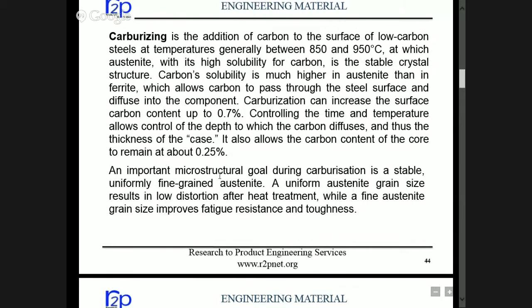So an important microstructure goal during carburizing is a stable, uniformly fine grain austenite. A uniform austenite grain size results in low distortion after heat treatment, while a fine austenite grain improves fatigue resistance and toughness. So the whole process results in a harder case for bearing the load, and a tough core in case of impact loading cases. And the stabilization is achieved through grain refinement.